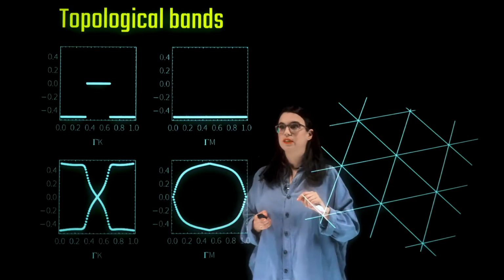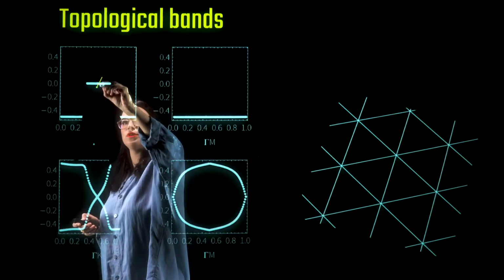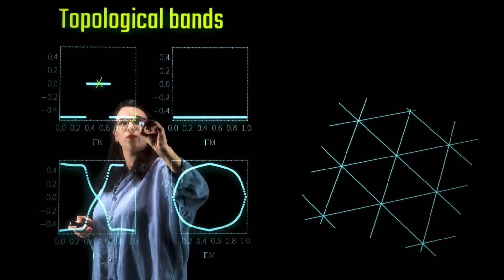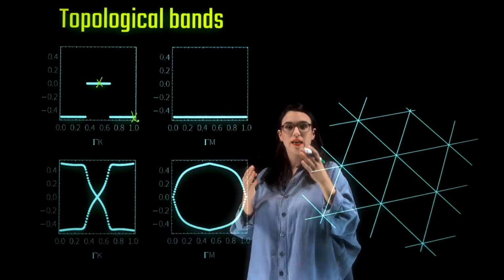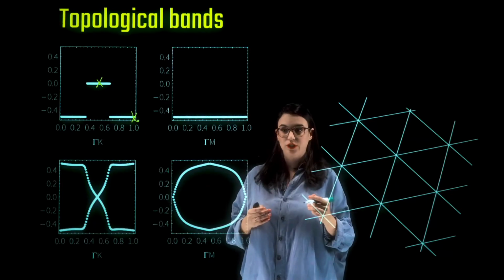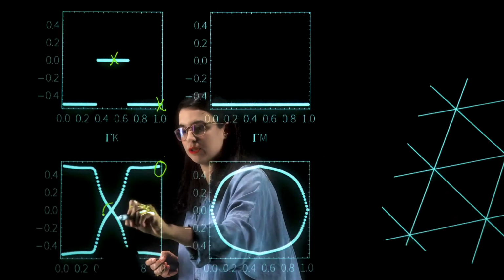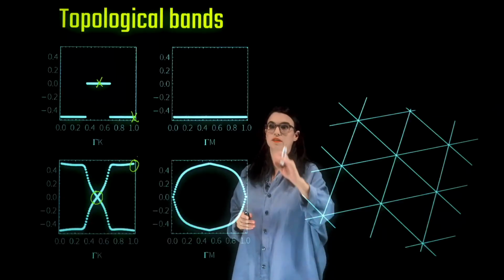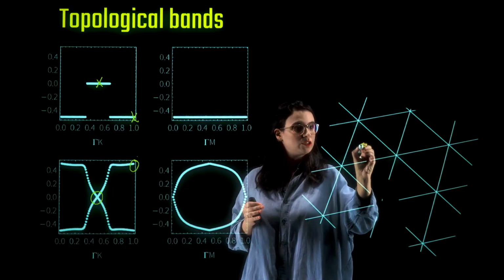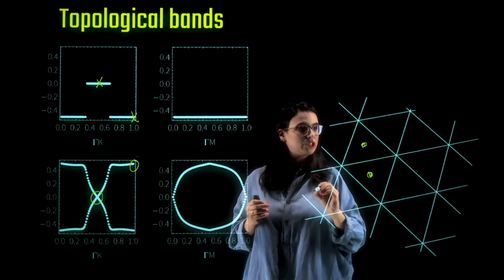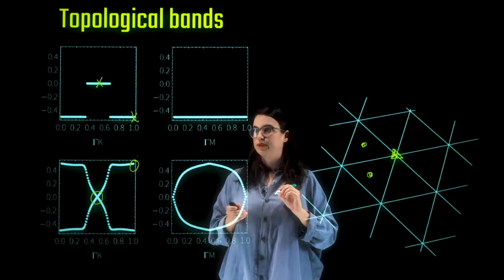And we can actually see, by looking at the time reversal invariant loops at k equals pi and k equals 0, that they are going to be located at different sites in the unit cell, in both cases, without spin-orbit coupling and with spin-orbit coupling. That means that without spin-orbit coupling, the states are composed of a combination of being on the 2b position, but also being on the 1a position.